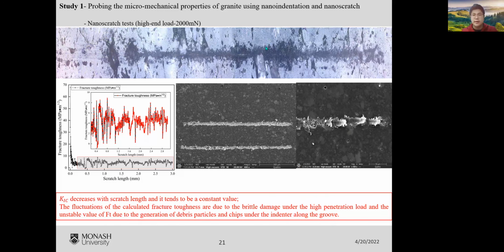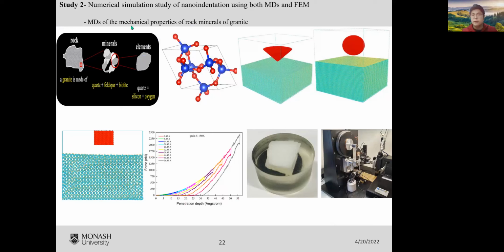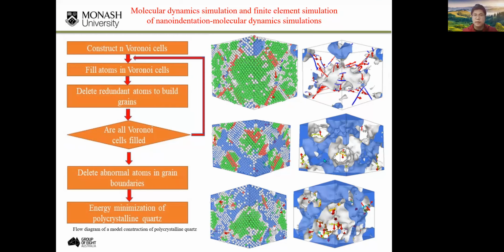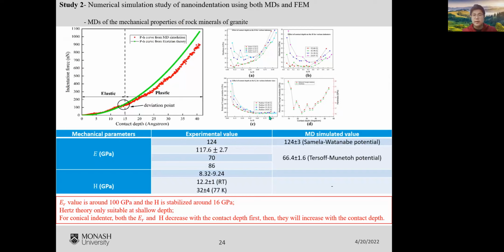Here comes my second study, that is the numerical simulation. We perform molecular dynamics simulation, and we study the impact of the indenter shape and also the impact of the grain size, temperature, as well as the indentation size. We compare the result with the nano-indentation experimental study, and it is found that the results agree well with each other. We also use molecular dynamics simulation to uncover the deformation mechanism underneath the indenter, and we found that for the conical indenter, both the reduced Young's modulus and the hardness decrease with the contact depth first, then they increase with the contact depth.